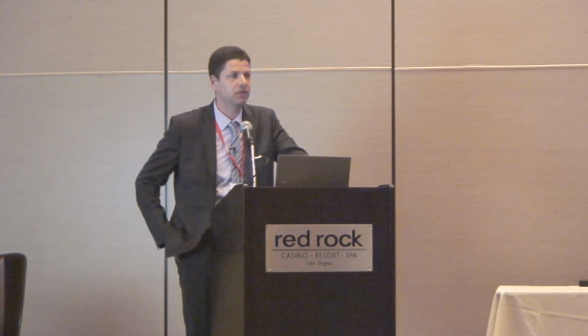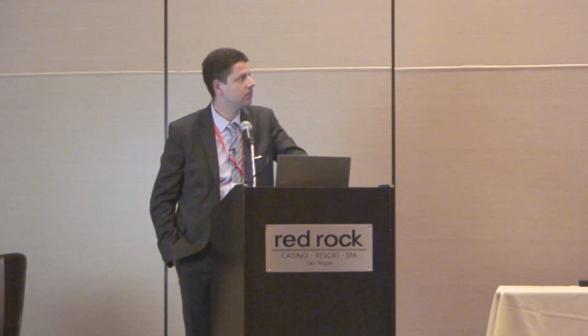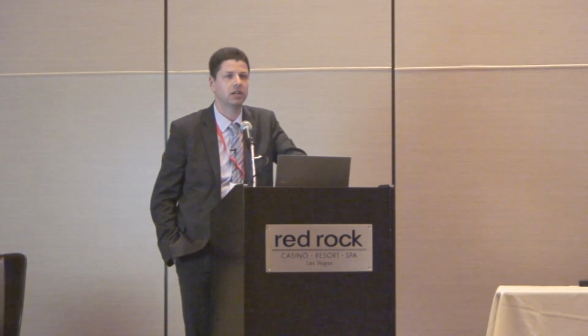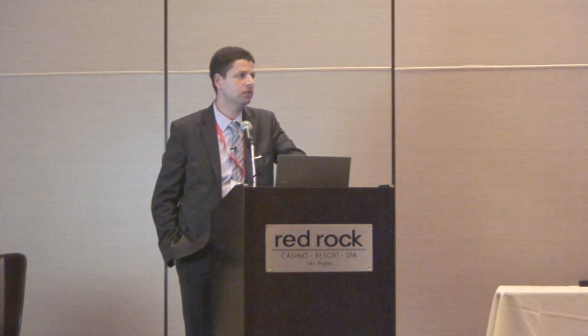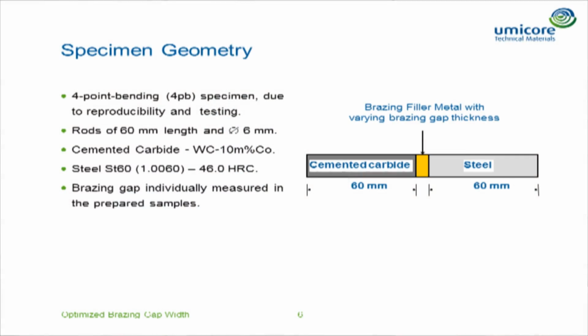Based on our experience with the other presentations and investigations we made in the past, we decided not to use a real part, and we decided to use a different kind of specimen, a 4-point bending test. And we had 2 cylinders of cemented carbide with a 10% cobalt binder, and here is steel. And in between, the different kinds of brazing filler metals were placed.